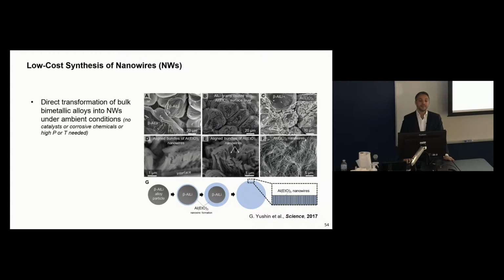So this is one simple example. When you have a bimetallic alloy between aluminum and lithium, if you put aluminum into alcohol, it's not reactive. But if you put lithium into alcohol, it forms lithium alkoxide that dissolves instantly. And so if you make these alloys between lithium and aluminum and put it into alcohol, then lithium dissolves. But when lithium dissolves, the aluminum becomes much more reactive, and it forms aluminum alkoxides. And what is fascinating is that it forms this aluminum alkoxide in the form of nanowires. If you wait long enough, you can convert this alloy particle into nanowires, and they become dispersed in the suspension or suspended in the ethanol.